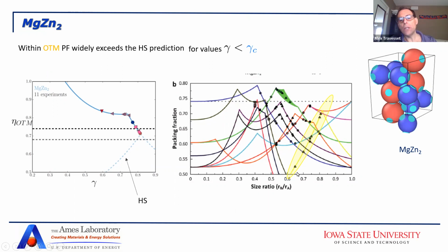So what you see now is that all these low packing fraction configurations actually become very high packing fraction. Not only that, it only happens on the left one, because on the right one, you cannot deform them. They are behaving as hard spheres, and that's exactly what the experiment sees.